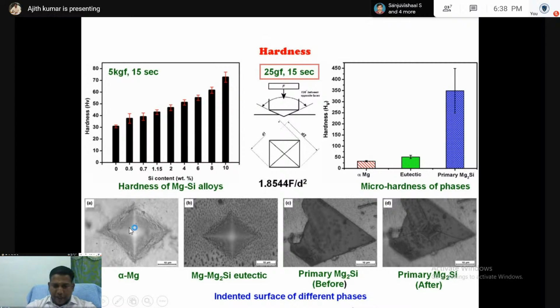Same metal, same places, same surface, different places we are indenting. The first place is the alpha Mg phase. In the alpha Mg phase, the hardness is about 37 HV. Then in the eutectic region, it is about 58 to 70, that range. Then if you check the hardness of primary Mg2Si, you can see a polygonal